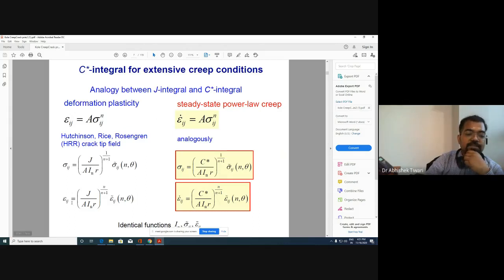What happens is that the stress and strain at the crack tip can be described by some equations which use the J integral. That is named the HRR singularity, because these equations were given by Hutchinson, Rice and Rosengren. It describes a place close to the crack tip where the J integral is also not valid, and that boundary is described by these equations. Basically the idea is, using the J integral you can find the stress and strain close to the crack tip. Similarly, using the C star integral you can find stress and strain rate close to the crack tip. But this part is not important at this point, so we will skip it.